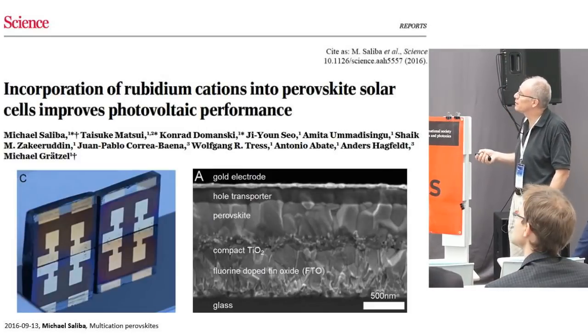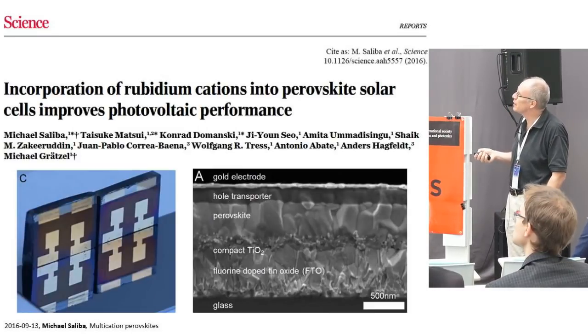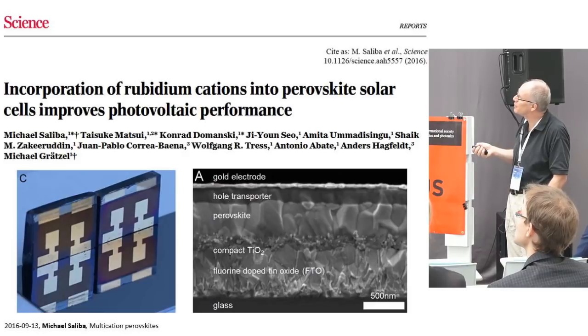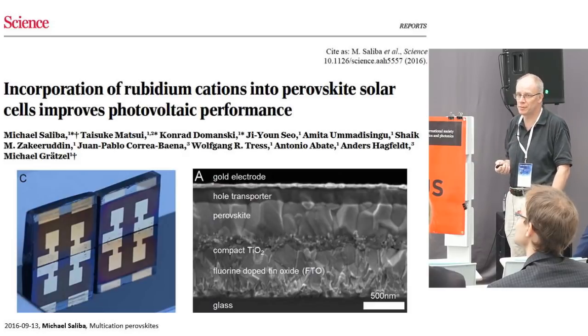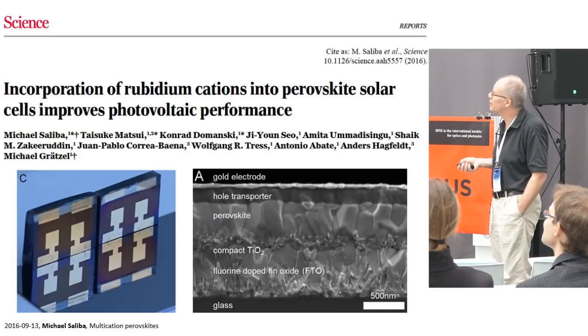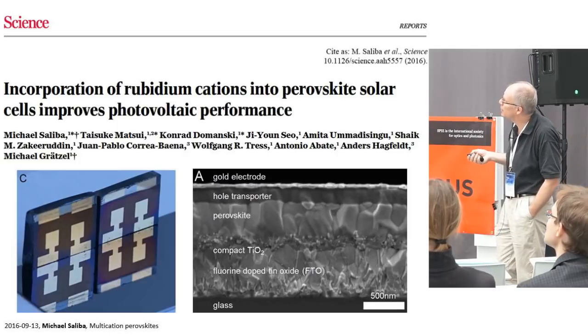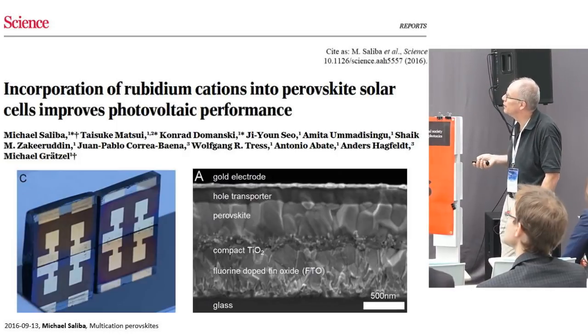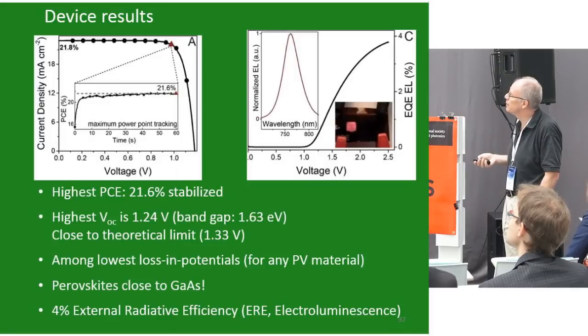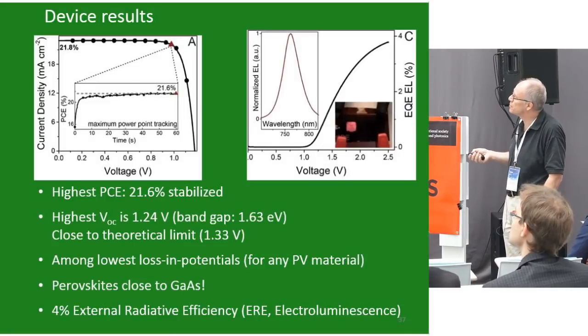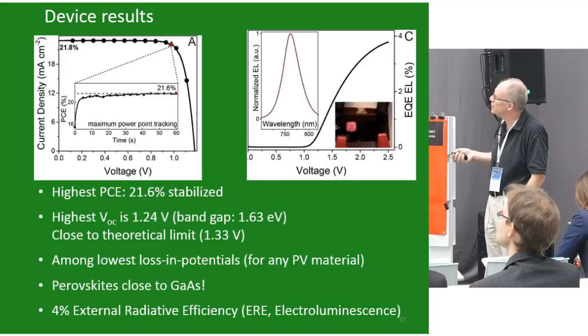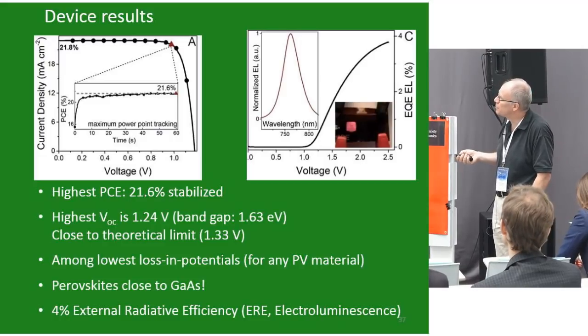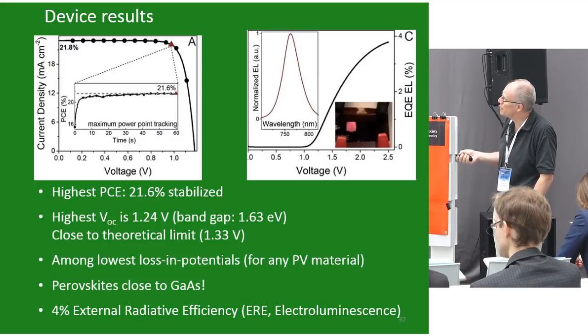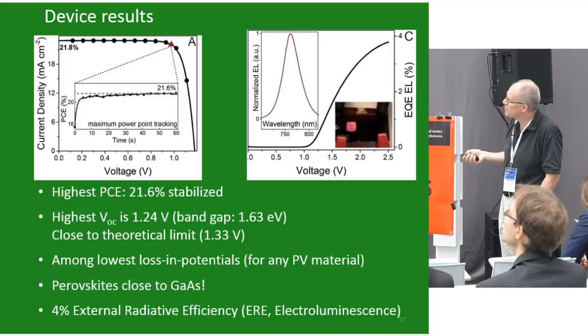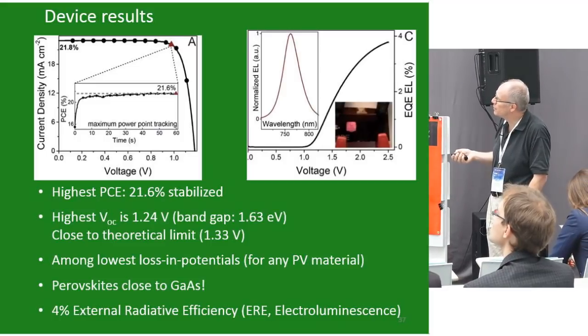And of course, Michael couldn't help, so he said, let's add a 4th one, and the next one in line is rubidium. So this became the quadruple mixed cation, and that we published with our best value published so far. So we had, with that, 21.6%, good stability, very high open circuit voltage, almost close to the theoretical limit. So that means a very high quality absorber and so on.